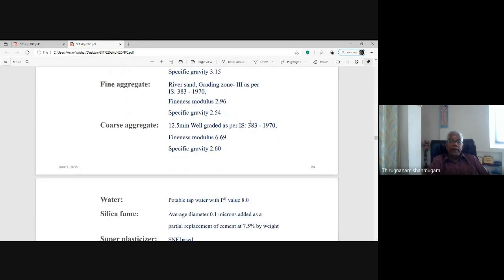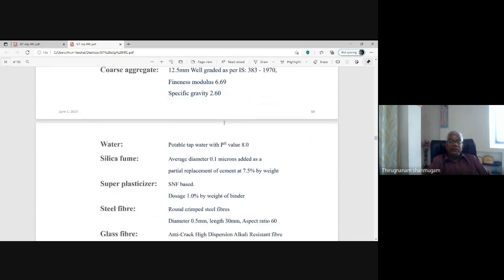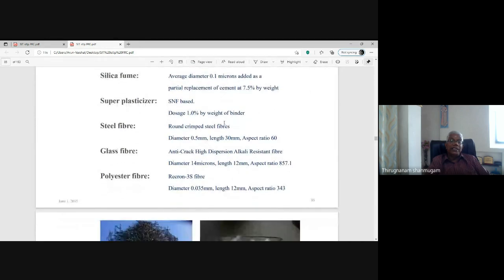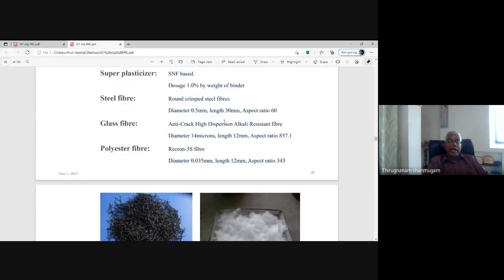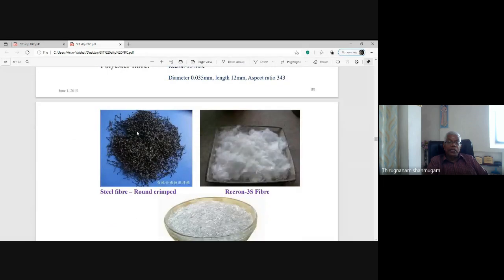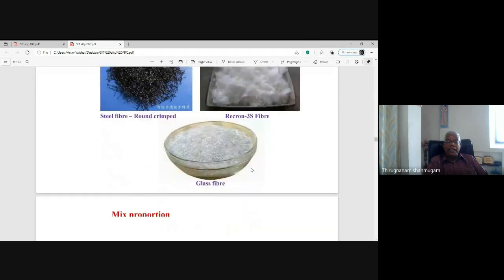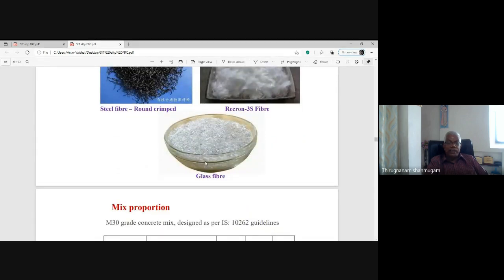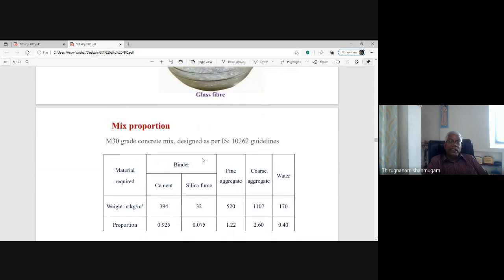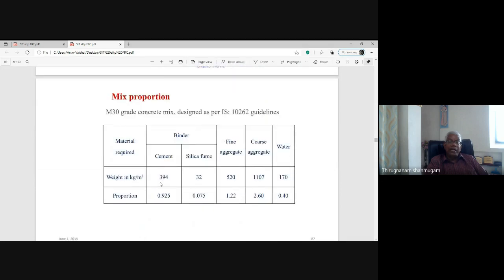Materials used are coarse aggregates, water, silica fume, superplasticizer, steel fiber, glass fiber, and polyester fiber. This is the view of the steel fiber, round crimped steel fibers. That is mild steel fibers, not stainless steel fibers, and the Recron 3S fibers and glass fibers procured in the market. Mix proportion is for M30 concrete, done by IS 10262.